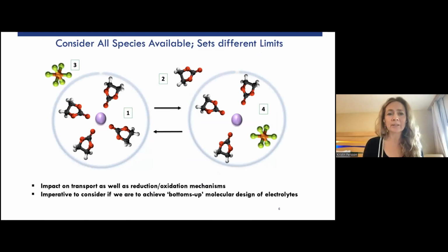So by minority species, I mean things like solvent separated ion pairs, where the anion does hang about, maybe not in the first solvation sphere, but it's close. And these things are typically in equilibrium with a contact ion pair kind of species, where the anion actually is present in the surrounding sphere around the working ion, whether that's lithium or magnesium or calcium or something else. And these minority species, which there normally are in lithium ion cases, but in other systems they may not be anymore, can have an impact not only on transport, that's pretty obvious because it changes the charge on your species in solution, but also on the stability of your electrolyte. These species can have different reduction oxidation mechanisms as well as stability windows.